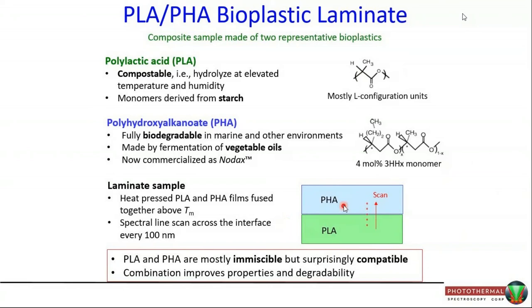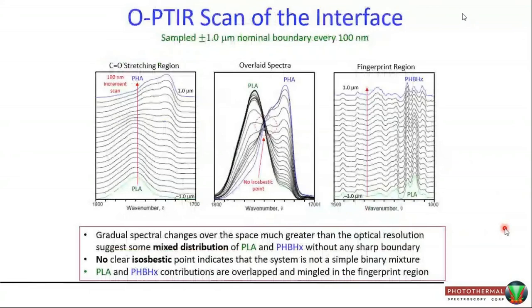And spatial scan of about every 100 nanometers is collected. So this is a typical spectra collected for the increment, in this case 100 nanometers increment from PLA side and PHA side. And we're looking at carbonyl stretching region, infrared. Of course, the spectral feature changes from PLA dominated region to PHA dominated region with gradual change. But if you overlay this carbonyl stretching band, you can clearly see that there is no clear isosbestic point.